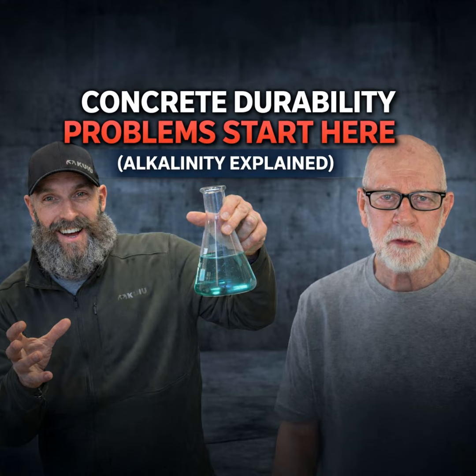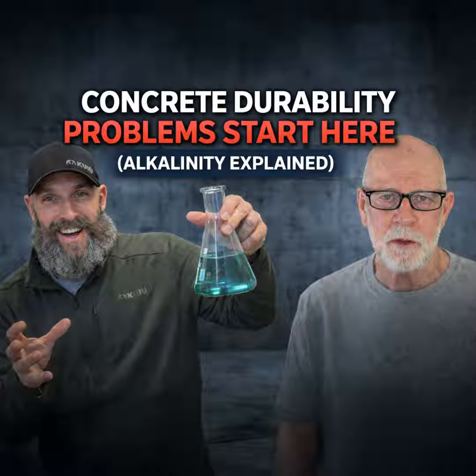What I use is a desktop demonstration. I'll get this vitrified pumice stone, which is really porous, looks like a big sponge. You pour water on it, but it's somewhat hydrophobic, so the water sits on it, doesn't want to penetrate. Then I'll take a saltillo tile where there's no apparent porosity at all. You pour water and it disappears.